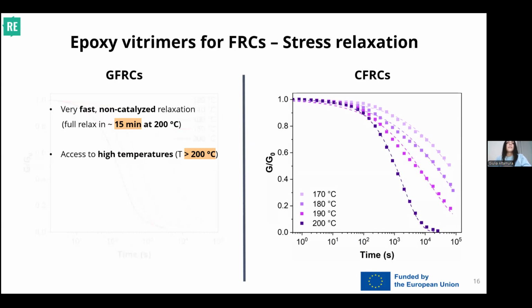In the first case, stress relaxation actually is pretty fast. We can relax fully our resin in 15 minutes at 200 degrees. But we could also push this relaxation further by increasing the temperature, since the only limit we have is the material degradation that typically starts occurring around 250, 270 degrees. Since these are our properties and they are more suitable for a glass fiber reinforced composite, we decided to produce with this material GFRC and to reprocess it.